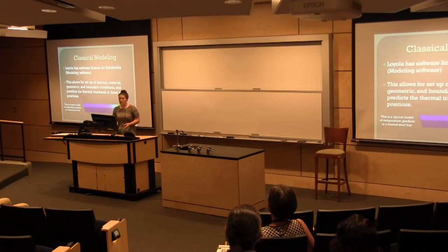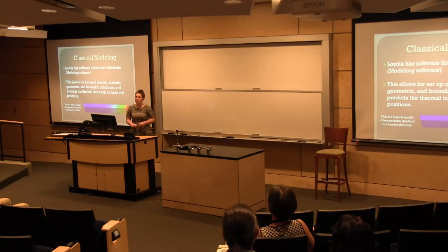So with the SolidWorks modeling software, we actually could put in the thermal, material, geometric, and boundary conditions that would predict the thermal transients at times and positions. So we're still working on that right now to change the variables here and there to get the most accurate model compared to our experimental setup. And as you can see on the bottom, this is just a typical temperature gradient of the steel bar that we'd be heating.